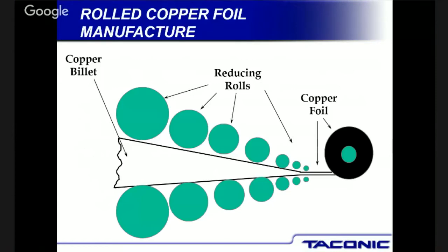And also, if you think about it, because it's a rolling process, the grain direction tends to be parallel to the panel. That means it's really good for those hinges on a printed circuit board on your computer. It's very ductile, very compliant and bendable. Electrodeposited copper, by the way, we get in a roll, and we actually take it and sheet it. So we cut it into sheets and put it on the material that you're buying.